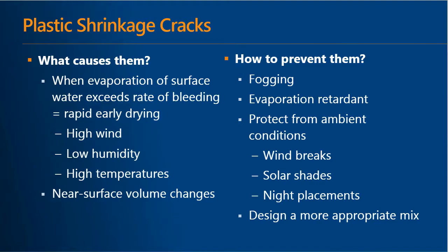And you can have ambient conditions that can exacerbate your propensity for plastic shrinkage cracking, and that may be high winds, low humidity, and high temperatures. And note, one of the best ways to prevent plastic shrinkage cracks are fogging or evaporation retardants. And you can also have protection from some of those ambient conditions as well.